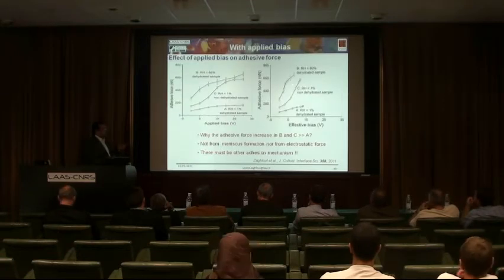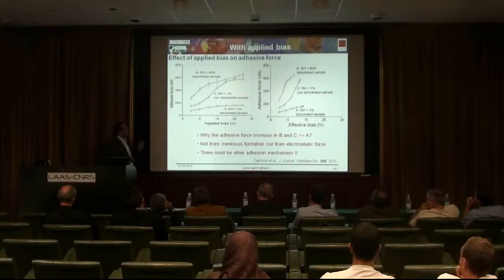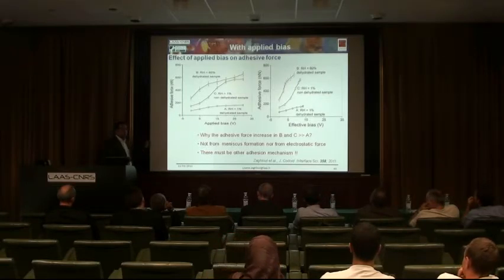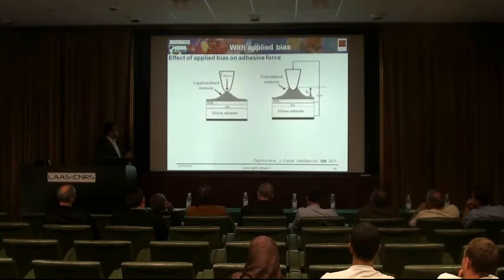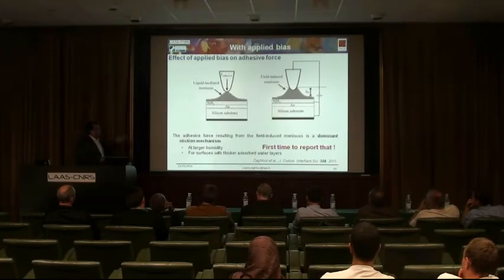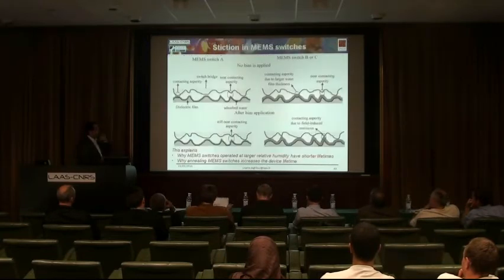So in C and B, the dominant mechanism behind increasing the adhesive force is not meniscus formation, and is not the electrostatic field. It is actually the multi-physics coupling between both, which is the electric field induced meniscus. And it was the first time to report this for MEMS devices.